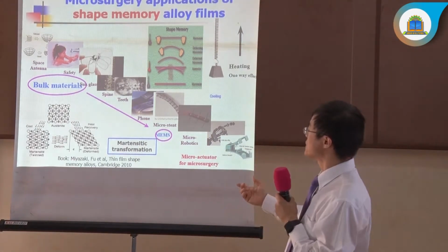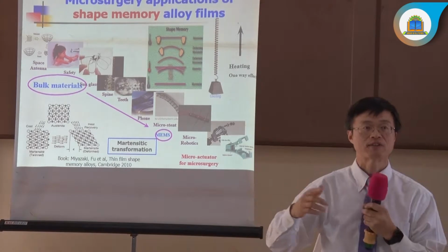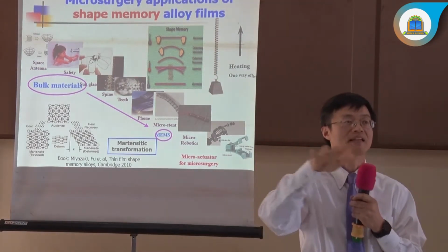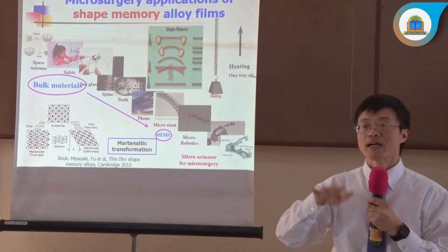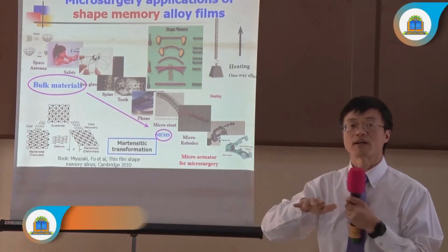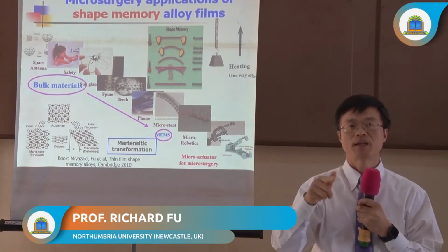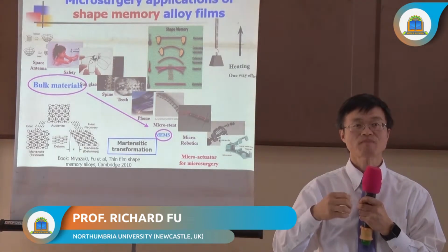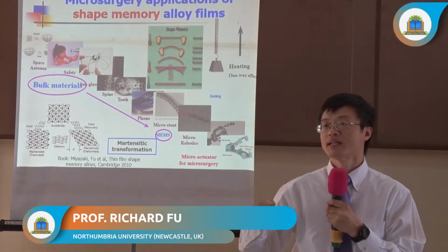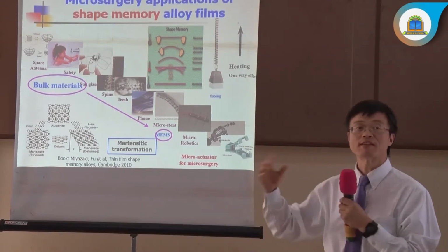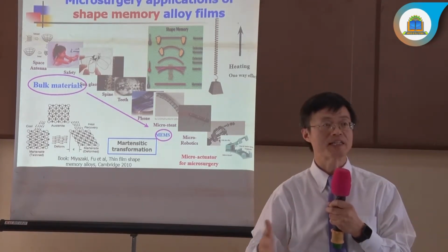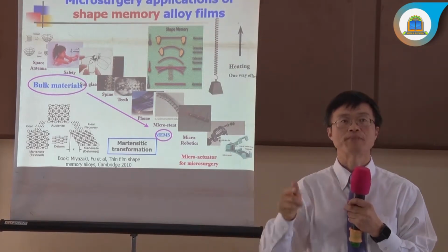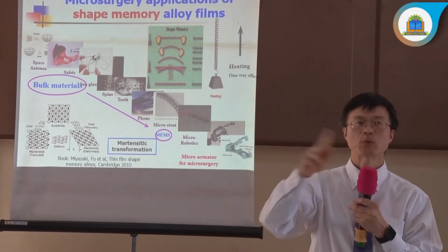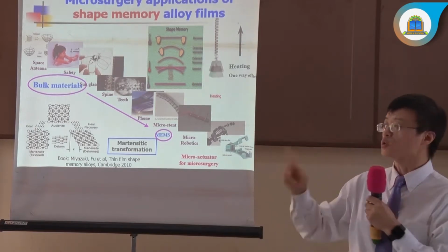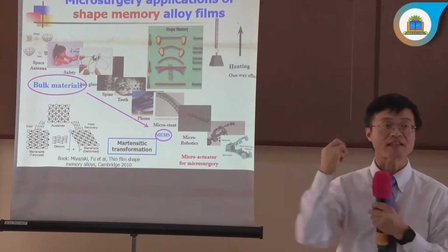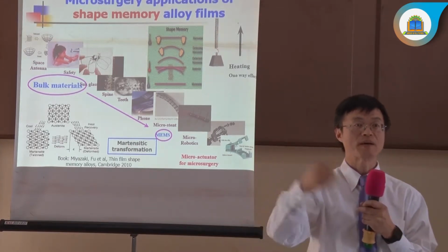So what's the principle of shape memory? Because the shape memory material is titanium nickel, titanium element and nickel element 50-50. At the room temperature, it's zigzag shape crystal. It's quite easy to deform. Once it deforms, if you heat this material, the material automatically changes the crystal from deformed martensite into austenite, into another crystal. During this transformation, the material just suddenly changes shape. It's returned back to original shape.